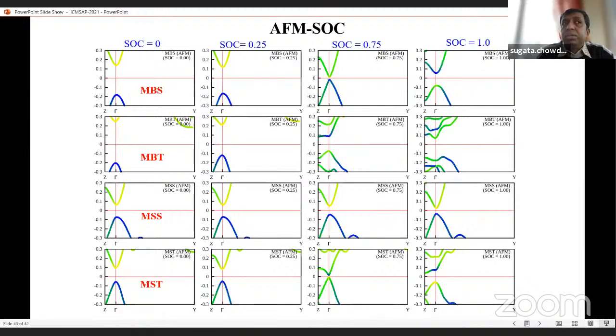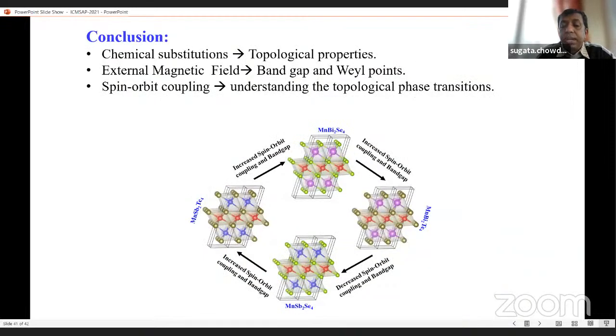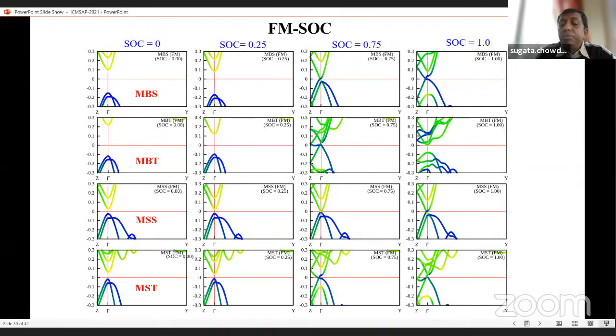at spin orbit coupling, that means the fully relativistic way, and how it is affecting. We notice that the relativistic effect is very pronounced in this system. If you notice here, if we apply the antiferromagnetic phase, this is a trivial insulator. That is the ground state. But what happens if we consider the ferromagnetic system? The ferromagnetic system shows that the spin orbit coupling is playing the major role.